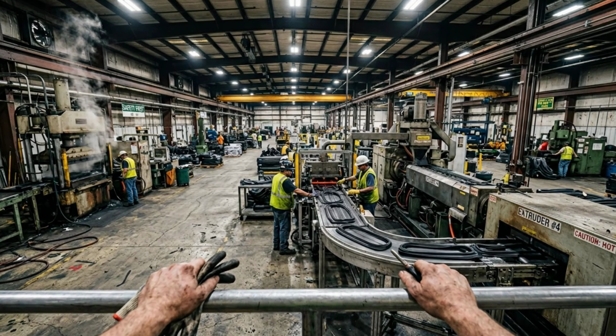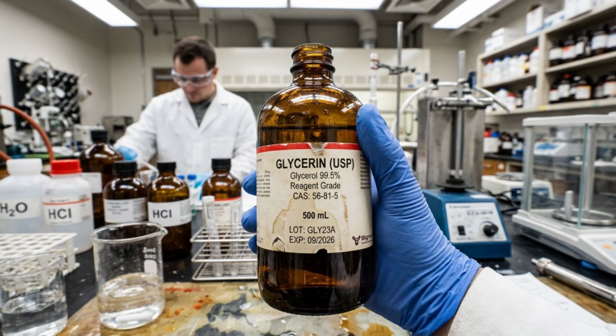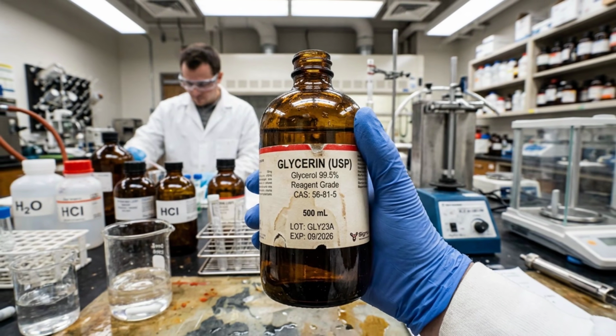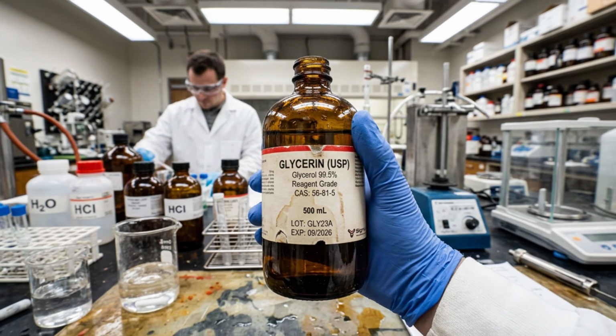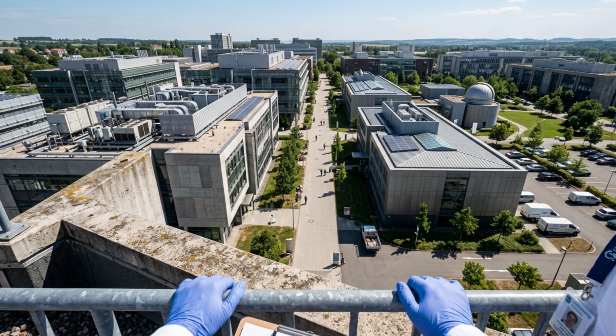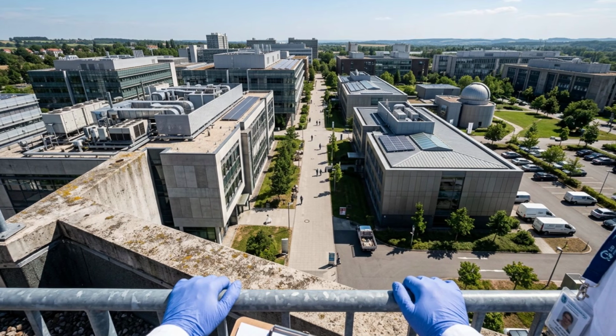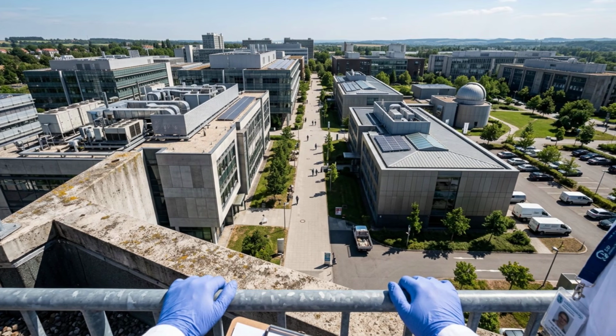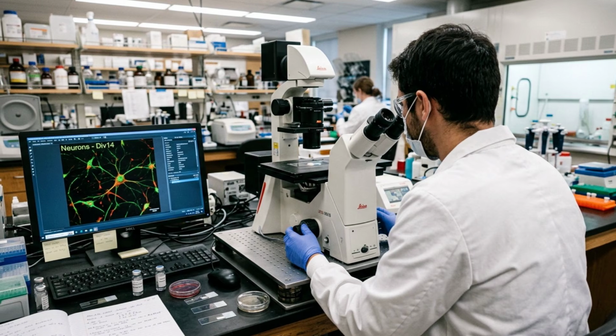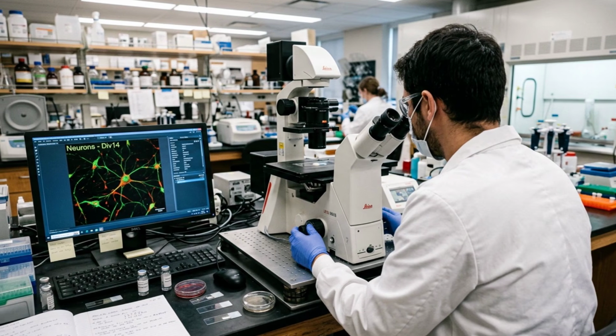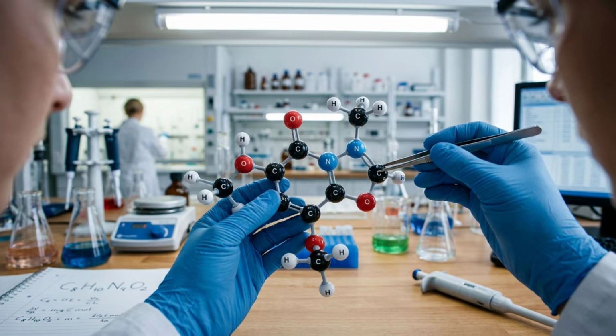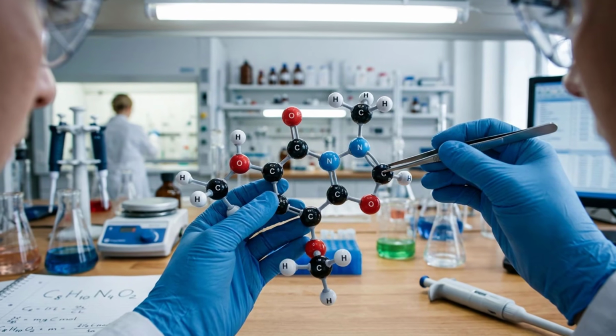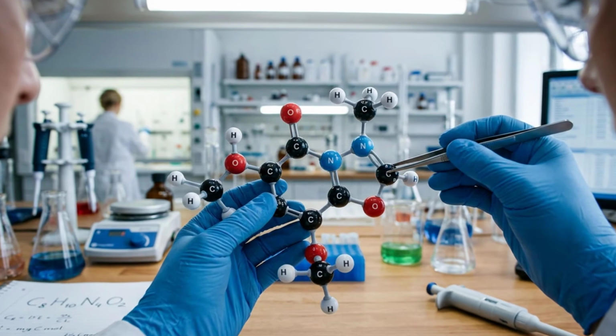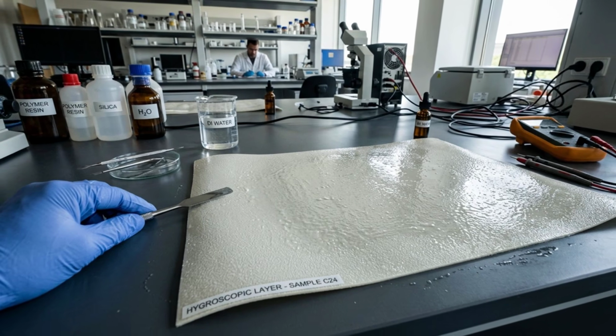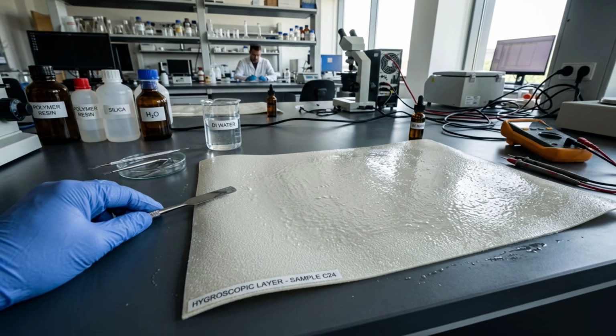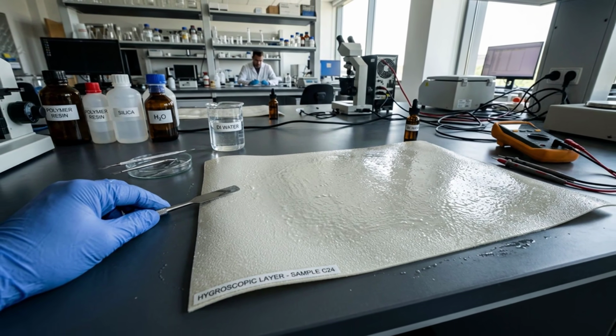The research identified glycerin as among the most effective penetrating humectants for preserving vulcanized rubber against surface oxidative degradation, brittleness, and cracking. The mechanism was documented: glycerin penetrates the oxidized surface layer of vulcanized rubber, reestablishes hydrogen bonding interactions with the polar oxidized polymer chain terminations, reduces surface scattering by restoring molecular level continuity in the surface layer, and provides a persistent hygroscopic layer that retards further atmospheric oxygen access to the polymer surface.